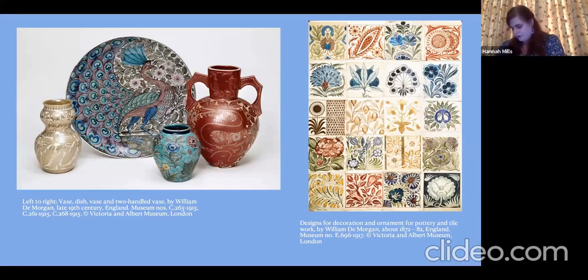Now, silver oxide gives a gold effect when successfully fired. And by altering the temperature of the kiln and also by adding different oxides, you can get a pale rose to lavender, depending on the metallic concentration. Now, the lustreware coating is quite fragile and very, very easily damaged.